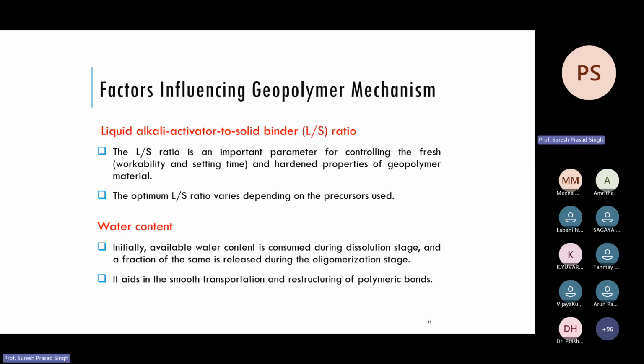Then the factor influencing the liquid alkali to solid binder ratio. It is similar to this. The liquid to solid ratio is an important parameter that we also determine for conventional cement. If you have more water, the structure will be porous. If there is less water, there may be segregation and so on. Similarly, here also there is an optimum liquid to solid ratio, which you have to find based on the source material: what raw material you are using, what type of alkali you are using, and the characteristics of your mortar. You have to find that out from lab tests.